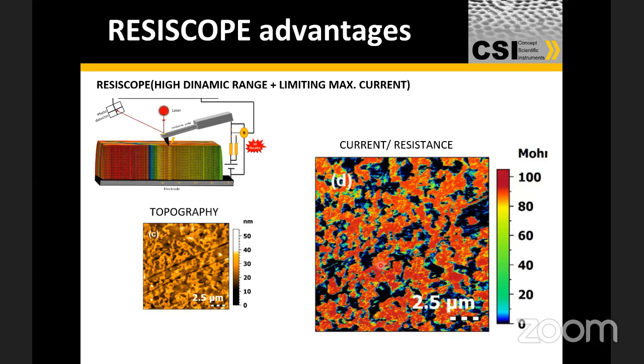Are these doped silicon or coated silicon tips? Actually, now we have a technology that lets us use direct diamond tips, so the entire tip is diamond, and that's down to about a couple of nanometers. These are quite expensive tips, but they give very nice data, sir.